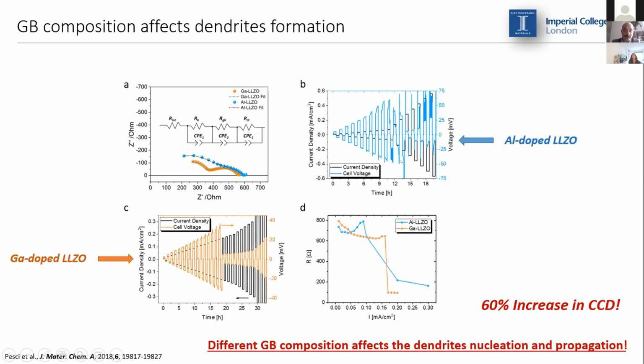And if we compare the electrochemical performances and the galvanostatic cycling for gallium-doped LLZO and aluminum-doped LLZO, we saw that systematically we had a critical current density, which is the current at which dendrite forms and the cell short circuits. For aluminum-doped, it was consistently 0.10 milliamp per centimeter square. But interestingly, for gallium, it was consistently 0.16 milliamp per centimeter square. So we do actually have an increase of about 60% in the critical current density.